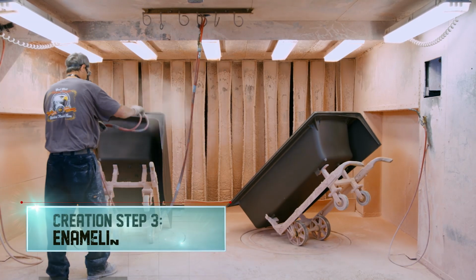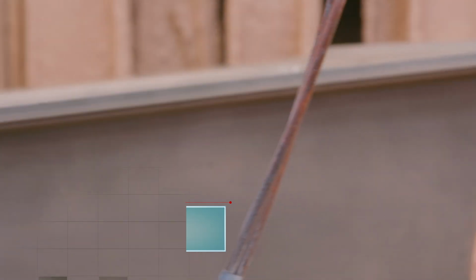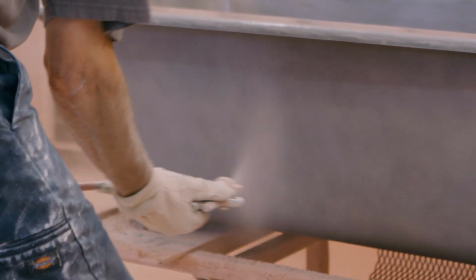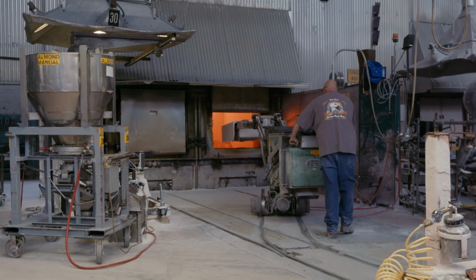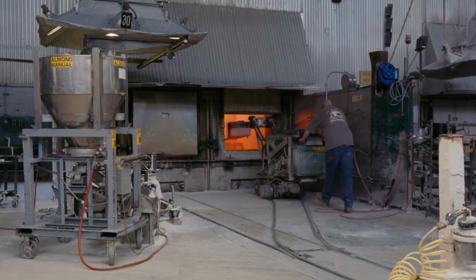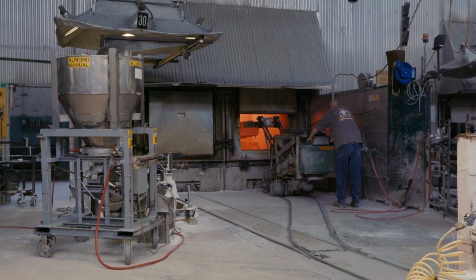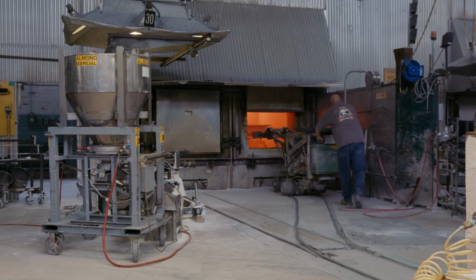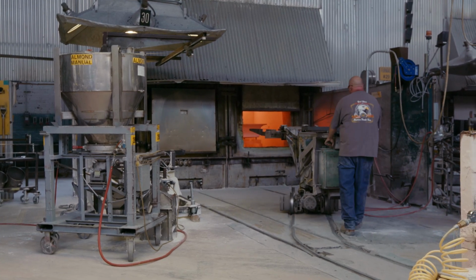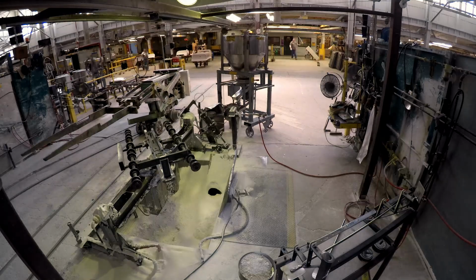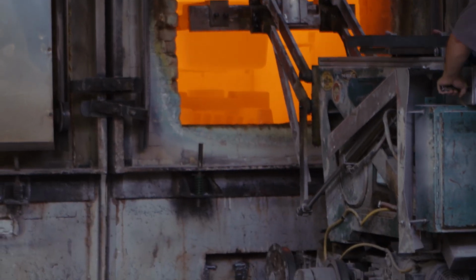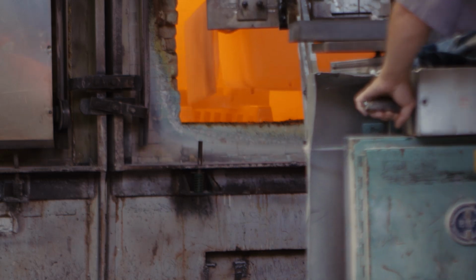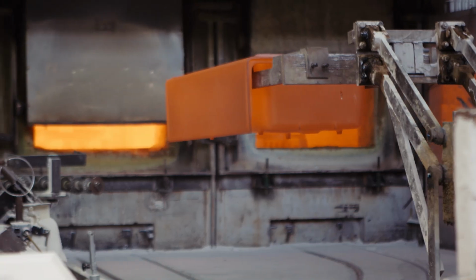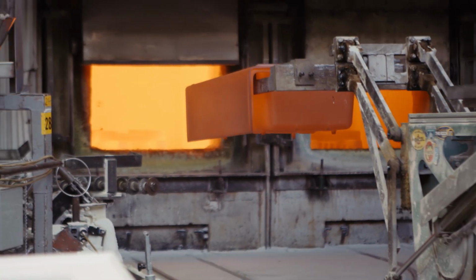First, workers sprinkle on a base coat made with a slurry of powdered glass. This first coat prepares the cast iron surface to adhere to the enamel. An operator wheels the tub into an oven where the undercoat bakes at 900 degrees Celsius for 10 to 12 minutes. Once the first layer is fused to the metal, the bathtub is heated in a second oven, now to 970 degrees Celsius.